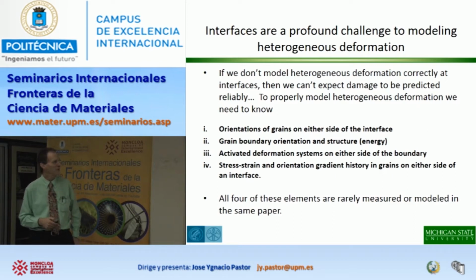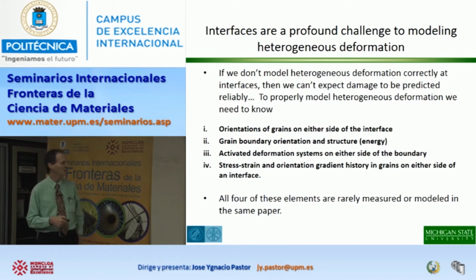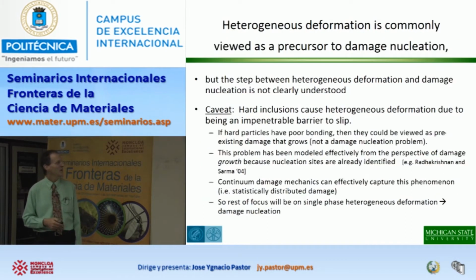But in order to really model what's going on at a grain boundary or a phase boundary, we have to know several things, some of which are not easy. We have to know the orientations of the grains on either side, the grain boundary orientation and its structure. Is it low angle, high angle, special boundary? What are the activated deformation systems on each side of the boundary? And what is the stress, strain, and orientation gradient in the grains on either side of the interface? That's complicated. That requires a lot of very good modeling to be able to understand or predict that. But basically, you rarely find all of that in one paper.